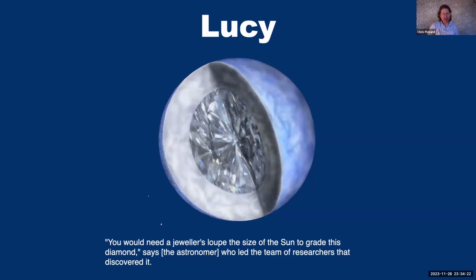Now, this is impossible for many reasons, but one of the reasons that it's impossible from a physical point of view is that diamond is actually a very open structure. The lattice of diamond has a lot of space in it. And if you remember from when I was defining enthalpy, the high pressures that you would expect to find in these astrophysical bodies would strongly penalize any extra space in the structure. So it seemed to me that this was a misleading picture. If you talk to the astronomers, they know that these stars don't have diamond. They talk about crystal lattices for their phases. But what we wanted to do is say, well, what actually might be the phase of these very dense forms of carbon?